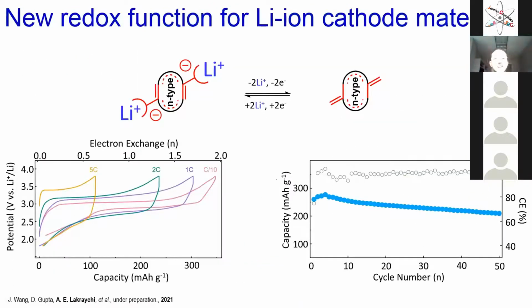So here, there is a new redox function that we are working on in the lab at UCL. I'm sorry I cannot show you the molecule now because it's still unpublished work, but I will show you the electrochemical performance of this molecule. So this molecule is lithium containing, is air stable, and has exactly the same characteristics as the previous ones, but with a different chemistry, with a different redox function. And this one actually can store high capacity. You are talking about more than 300 milliampere hour per gram if you exchange 2 electrons or 2 lithiums, and the potential is pretty much at 3 volt. But, capacity is more, we have a moderate stability after 50 cycles.